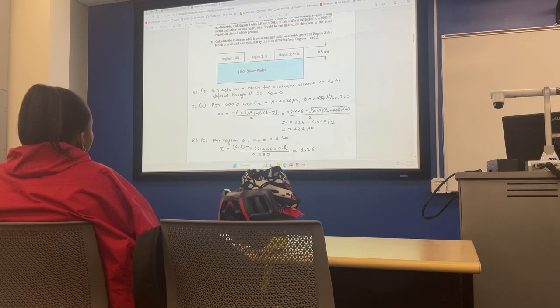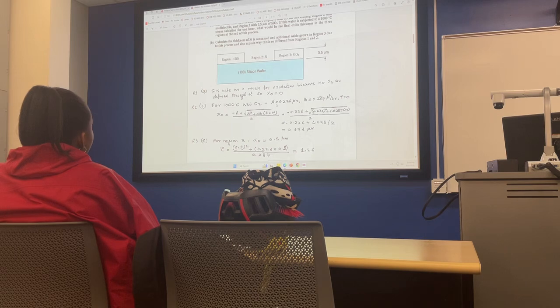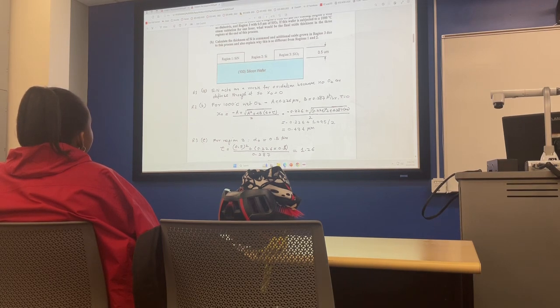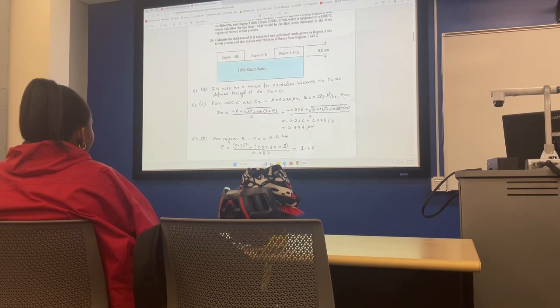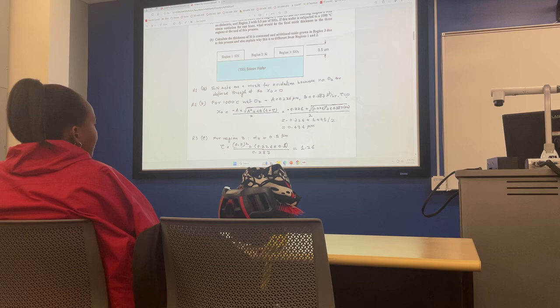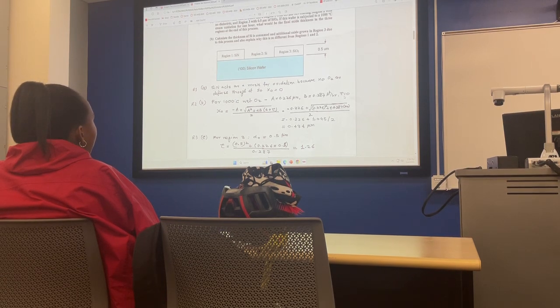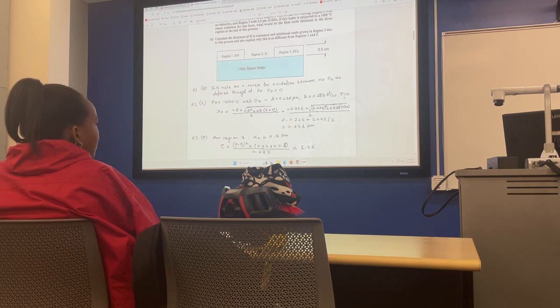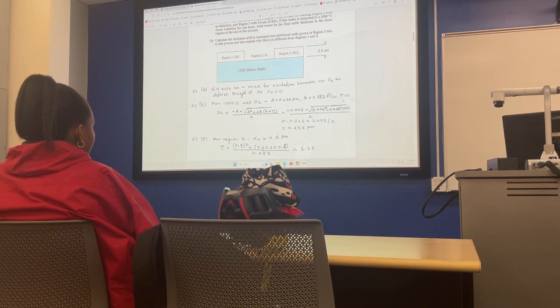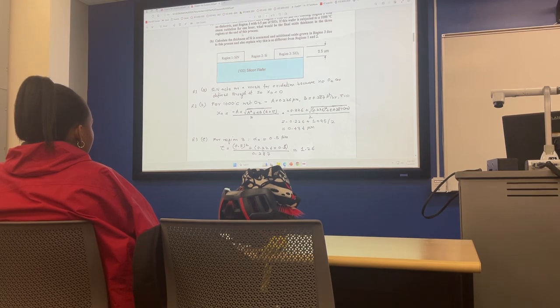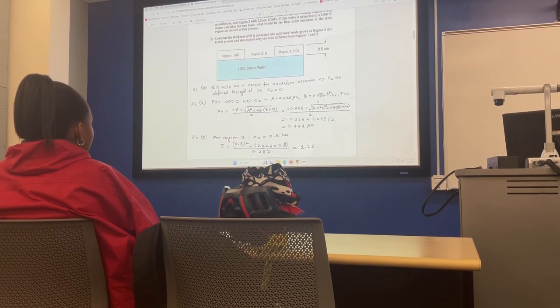The second one was very straightforward. It is bare silicon and we are doing steam oxidation. So you are given 1000 degrees, you know A and you know B, and you have to use tau equal to 0 here, because some of you took the tau for the dry oxide. But remember, for wet oxidation on bare silicon, tau is 0. Only when you are doing dry oxidation, so some of you used the number 0.37, which is written somewhere in the table, but we forgot that this is steam oxidation. So you will just use A and B, and that's it.